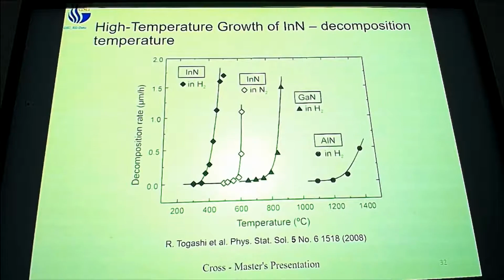Materials are well defined, well studied. They work the way they are. And they're grown at 1100, 1200 degrees Celsius in MOCVD. There are other methods to grow them that have other temperatures and other pressure regimes that they work in. But when I look at indium nitride, it basically breaks down way before I get to those temperatures.